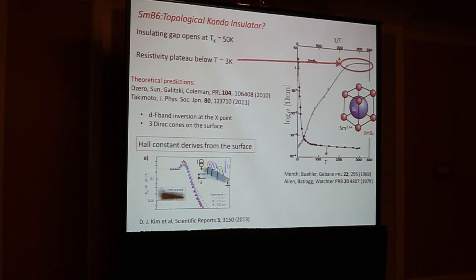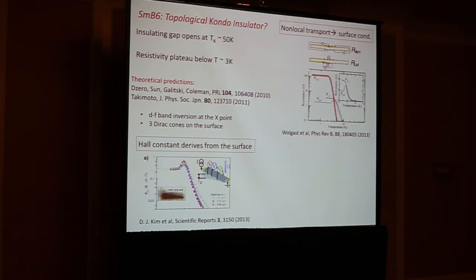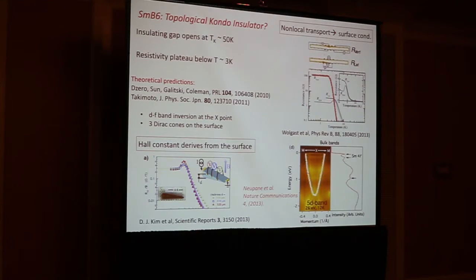Experimentally, this led to studies to try and see if there's a surface conductivity, and this is one of the early studies by Kim et al., showing that the Hall constant derives from the surface. As you change the thickness of the wedge, the Hall resistance doesn't change, showing that this is a surface contribution. You can also look at the surface conductivity by doing non-local transport experiments, the work of Wolgast et al. And finally, you can look at this system using ARPES, and you can confirm that the d-band crosses at the X point.